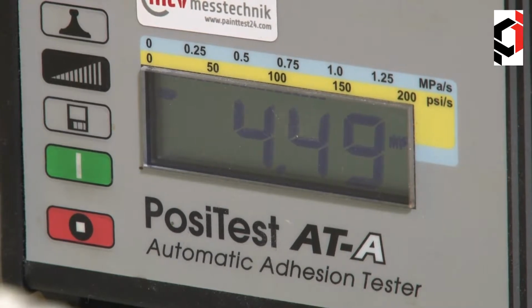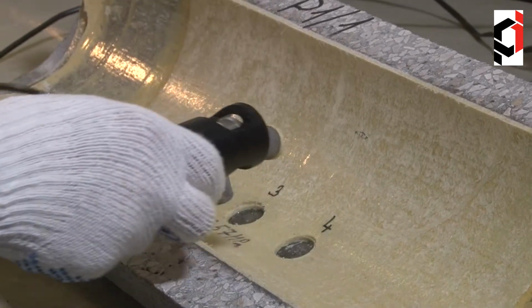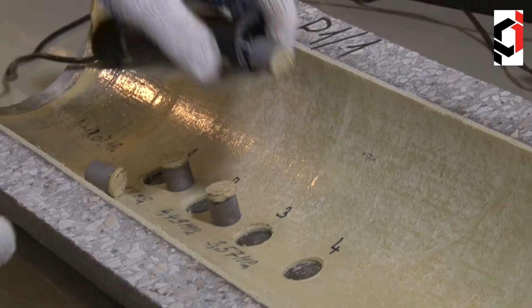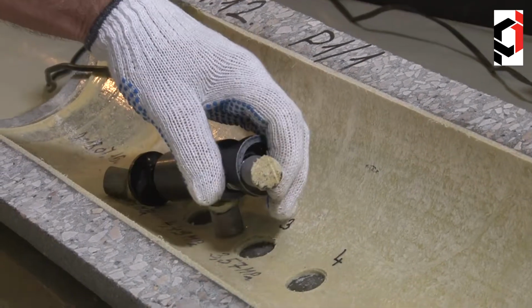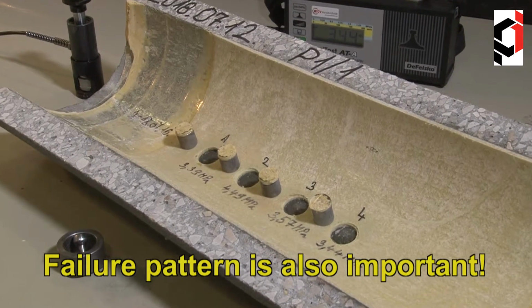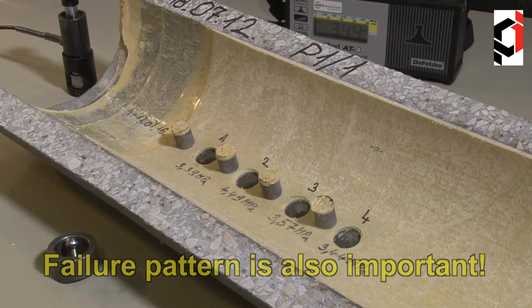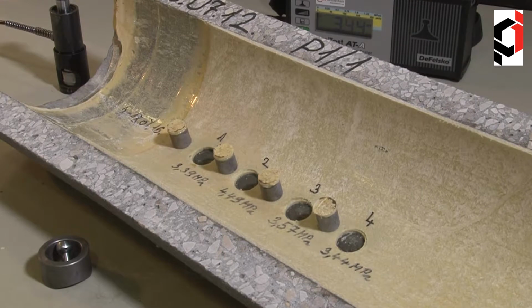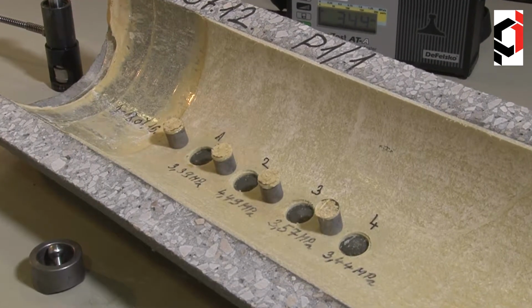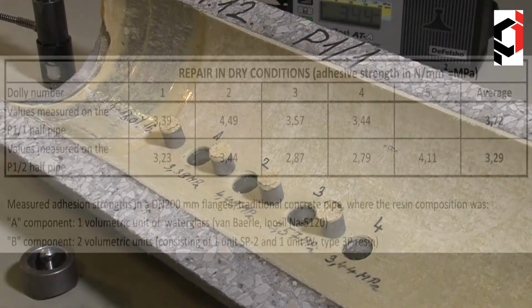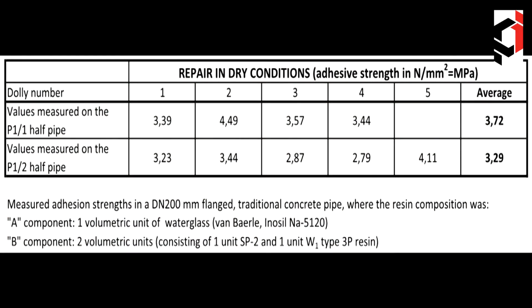It is also important to record the failure pattern. Did the glue separate from the lining, or the lining from the pipe, or the pipe material failed in itself? We cannot measure high adhesion values even with the best resins if the upper measurable limit is the own tensile strength of the concrete. This table shows the test results of the repairs made in dry conditions.